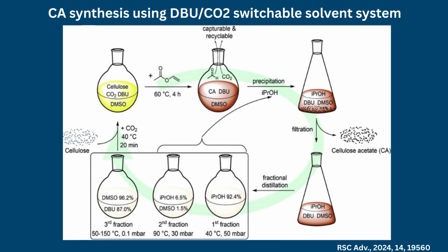Recent advances in green chemistry have introduced homogeneous acetylation methods employing DBU/CO2 switchable solvent systems. These catalyst-free processes minimize cellulose degradation, allow precise control over degree of substitution, facilitate solvent recycling, and significantly reduce hazardous waste generation.